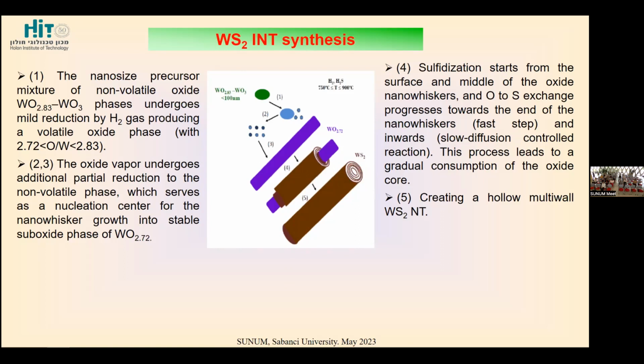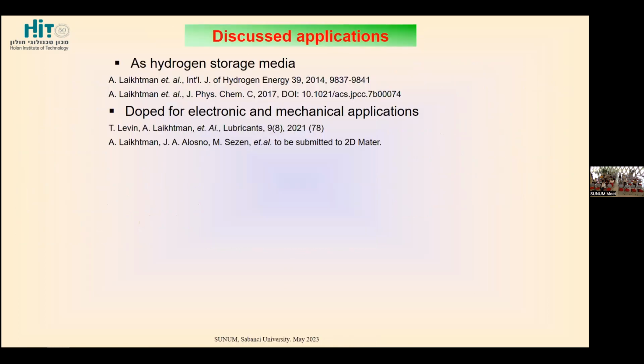This material should be pure, more than 90% purification, both in structure and in chemical composition. Sometimes we have some oxide, but generally we can remove it to a very low concentration. I will discuss a number of applications. The first one is our attempt to use them for hydrogen storage. And the next one, based on this hydrogen storage result, is doping for electronic and mechanical applications.